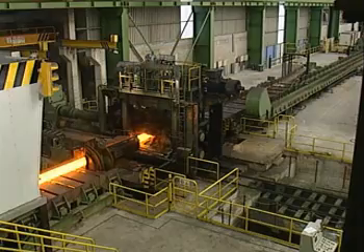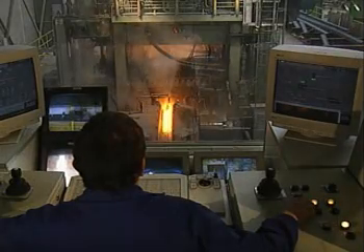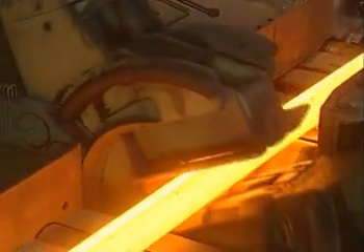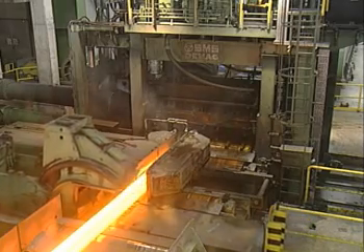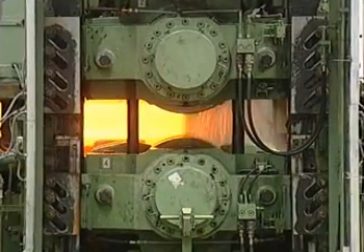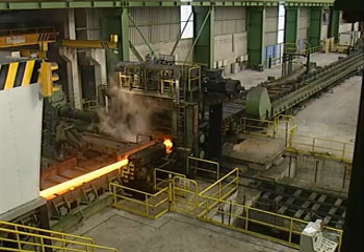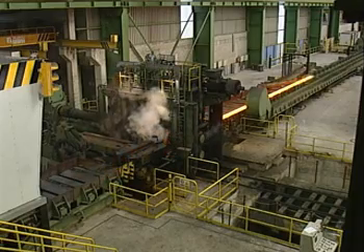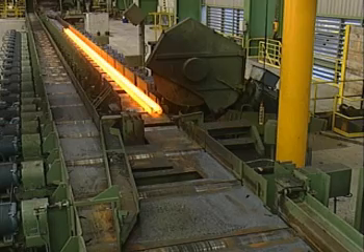The breakdown reversing stand, with maximum roll force of 4,500 kN, features a fully automated rolling process. Side guards and grip-type tilters reliably position the material to be rolled before each subsequent pass. Mill guides are not needed for roughing in open grooves. Roughing of beam blanks and blooms takes place in three to seven passes. If necessary, the rolled material can be cropped to prepare it for the initial pass in the following tandem group.